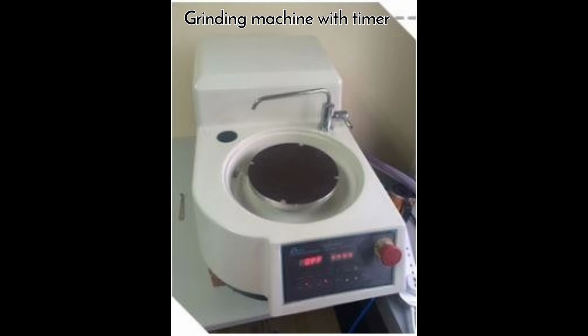To obtain accurate data during the experimentation and analysis, the peat samples must undergo a preparation process. The raw peat samples that are taken from the area of study must be turned into fine powder form by using the grinding machine. After that, the raw peat sample that is now in fine powder form will be compressed at 5 tons of pressure by using the hydraulic compressor